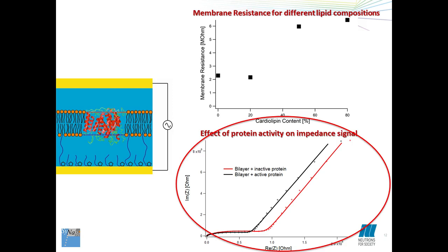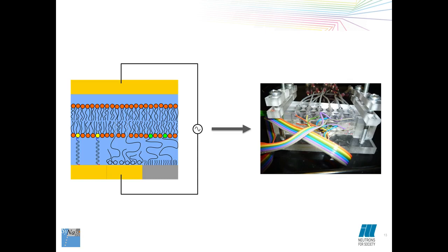As the protein creates a transmembrane current, this influences the resistance of the lipid bilayer, which is again visible in impedance spectroscopy. Combining these two methods, I identified favorable properties for the biomimetic fuel cell and was able to produce stable membranes with high fractions of incorporated membrane protein. With the analysis of the neutron reflectometry data from the other tethering systems, I will be able to evaluate their suitability for protein incorporation and their influence on its activity.